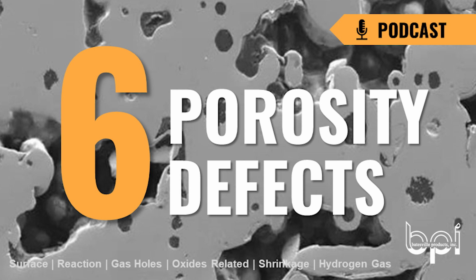Even at a macro level, if you're machining it, a lot of times you'll see a little bit of porosity that you've picked out as you've machined it, but you'll see a tail or a stringer come out from behind it. If you're pouring in a sand casting and you're pouring too high or your gating's not correct and you're filling too fast, you can get the oxide. It can happen in anything, but the faster that you fill, the more prone you're going to be to having them. You could see an oxide trap behind a filter.